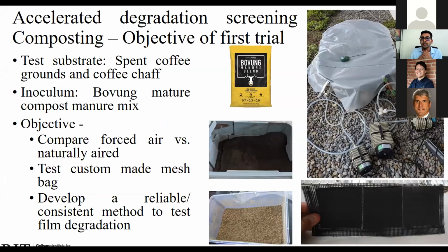And we chose composting as a screening process. As Professor Carlos talked about, some of these films, when they are pristine or fresh, take a long time to biodegrade or don't show any signs of biodegradation till 180 or 200 days. So we wanted to come up with a solution where if Ivan or the next student, Swapnil, gives me their films to test, I'll be able to give them an answer back within 60 or 90 days, saying that this particular film is doing well, or this particular method is working well in biodegradation versus this particular method is not. Composting was a good way to accelerate the biodegradation of these, and the literature does support that. Also, the films technically are chosen or certified compostable.